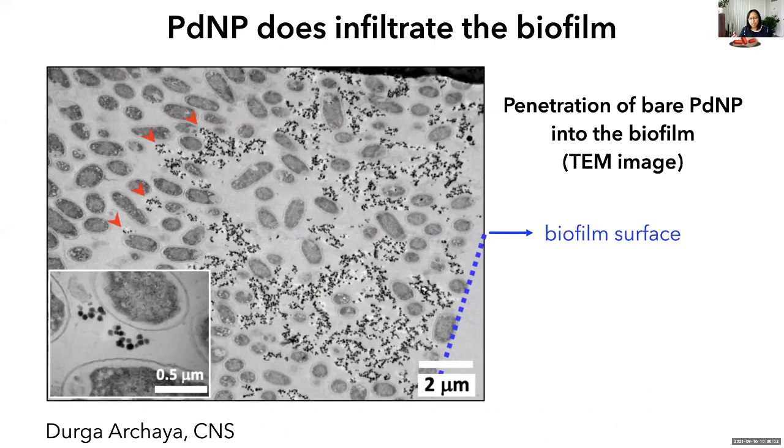So very lastly, this is my last slide. We heard about penetration as a problem in nanoparticle application. So that is also one area in the group that we just started to tackle. And this is preliminary data showing that when we incubate this bare nanoparticle, so no peptide, nothing, just the bare nanoparticle, in our biofilm, and then took a cross section and looked at the image in the TEM, we were able to see that this PDNP could actually penetrate the